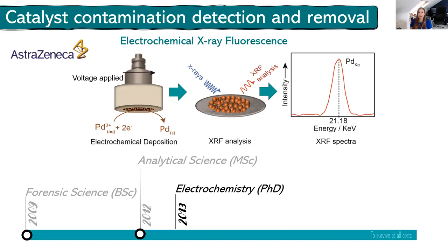Now, the innovation around this technique was really that our electrode material is made of boron-doped diamond. We use boron-doped diamond for two reasons. One is that diamond in and of itself is not electrically conductive, so we can't use that as an electrode material. So when we grow diamond, we actually have to put boron into the growth to create an electrode that is conductive. And the other thing is that both boron and carbon are actually